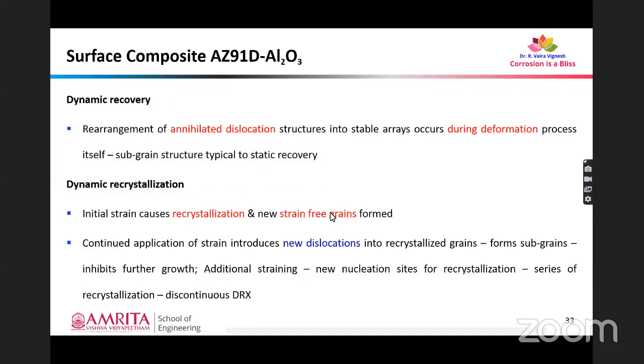And if this happens simultaneously, the temperature and straining happening simultaneously, the material will be subjected to dynamic recovery and dynamic recrystallization. So this dynamic process exactly happens right beneath the FSP tool. The rearrangement of annihilated dislocation structures into stable arrays occurs during the deformation process itself. And the subgrain structure is typical of the static recovery process.